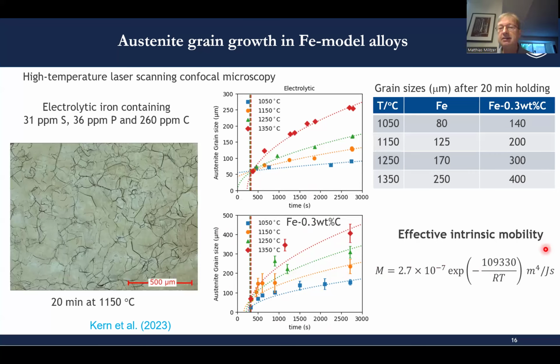effective intrinsic mobility. And what I mean with effective, it's not the classical intrinsic mobility for pure iron. It's the mobility of the grain boundary that carries the carbon atoms. So very much what I had shown just earlier today in terms of the molecular dynamics simulation, that carbon would enrich at the migrating interface. And this intrinsic mobility then provides the starting point to account for which impurities may actually reduce the grain growth rates in electrolytic iron.